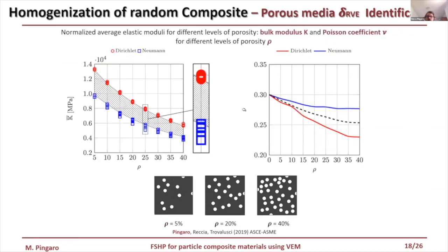After that, we study the sensitivity to the porosity. We analyze different levels of porosity, starting from 5% to 40%. As intuitable, the homogenized moduli decrease when the porosity increases, such as the bulk modulus here reported. While the homogenized Poisson coefficient has a particular behavior. It decreases with increasing porosity. That is normal. But the two bounds are exchanged, in the sense that the Neumann boundary condition is the upper bound of the solution, and the Dirichlet boundary condition is the lower bound of the solution.